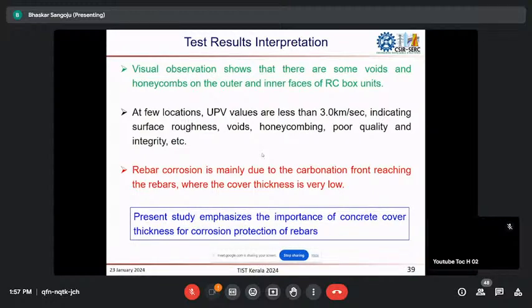So that means this study emphasizes the importance of concrete cover thickness for corrosion protection of rebars. And based on these tests, we gave the recommendations that the RC box units can be used, provided some precautions have to be taken where the cover thickness is very, very less and where honeycomb voids are there. There, we asked them to go for protective coatings. Those coatings will act as a barrier for the entry of moisture and oxygen.